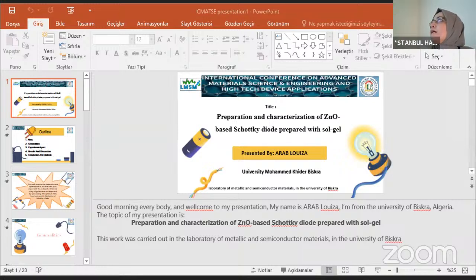Here we study only the films deposited on glass, because if we study the films deposited on ITO glass, we can't get the resistivity of the films because ITO has high conductivity. So the figure shows the variation of these parameters. Here we have the conductivity in red color. We have recorded a high conductivity for the ZnO co-doped with aluminum and indium. And this result is very important for our study of the Schottky diode.